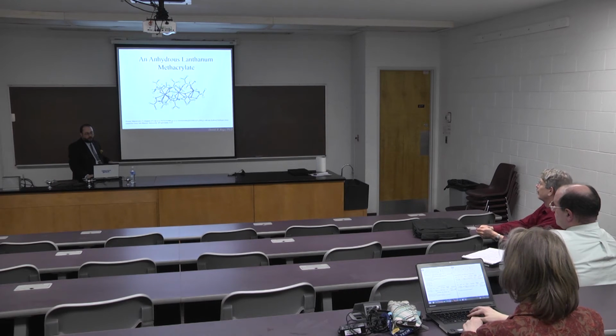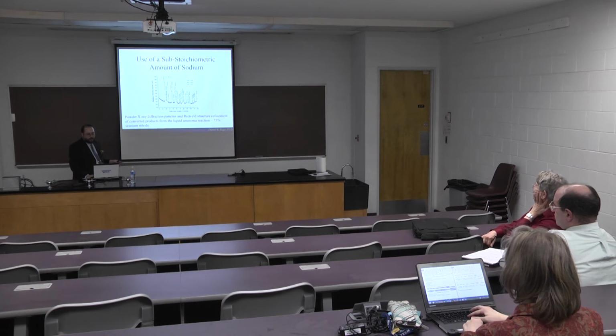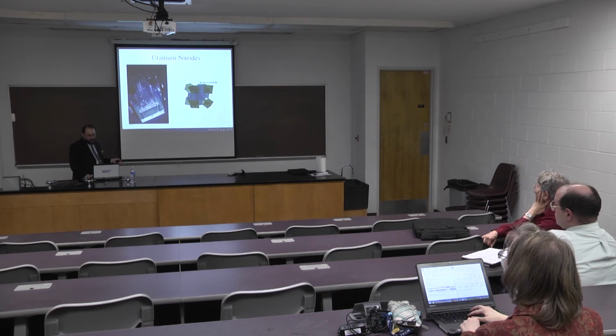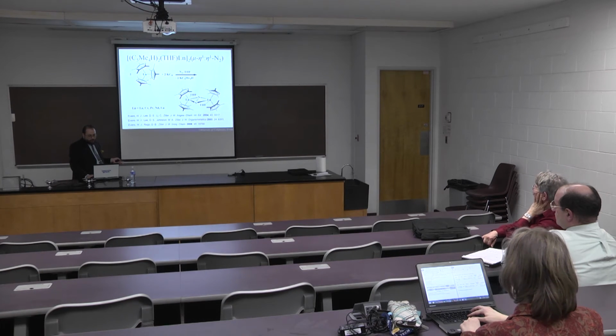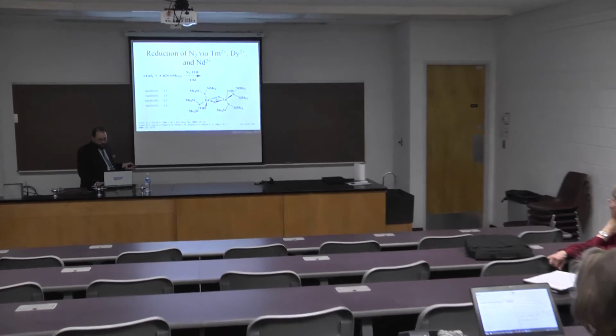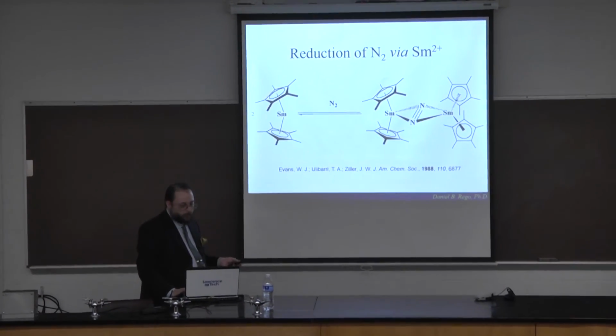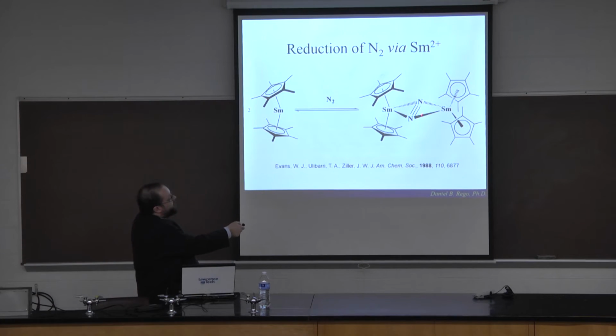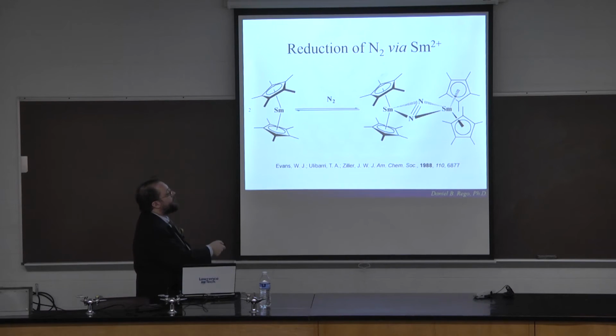But a little bit more interesting in regards to that question, and I didn't mention it because I didn't think I had time at the beginning, you'll notice that with the samarium compound I have here, I still list nitrogen as being 3 bonded, even though I said it's reduced and this is 3+. Well, it turns out in the crystal structure, this nitrogen-nitrogen bond was about 1 angstrom, which is a little bit shorter than free dinitrogen. And N2 with 2 additional electrons should have a bond order of 2, coming out to around 1.25 angstroms.